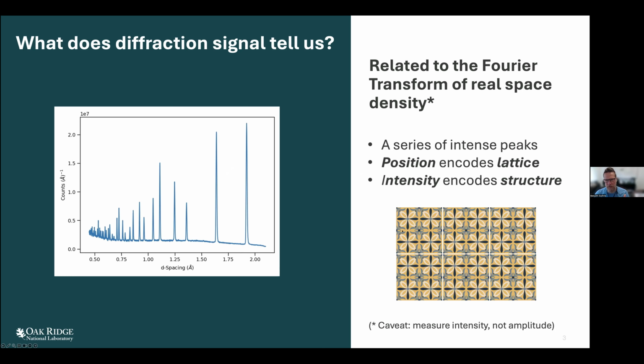And a really nice analogy I like to use is to just imagine tiles on a wall. So the position of the Bragg peaks is telling us about the shape, the size of the tile, and the intensities are telling us about the pattern inside the tile. And mathematically, this boils down to the Fourier transform, and you can loosely think of the diffraction pattern as being the Fourier transform of the real space scattering density, which will be electrons in the case of X-rays or nuclei in the case of neutrons. With the small caveat I've noted here that what we measure is intensity and not amplitude. Otherwise, things would be very simple and we'd just do a Fourier transform and we'd get everything.